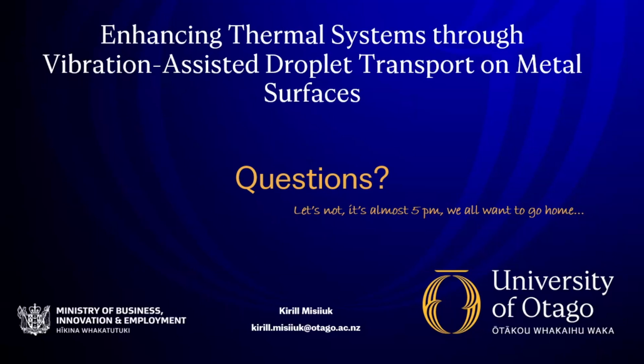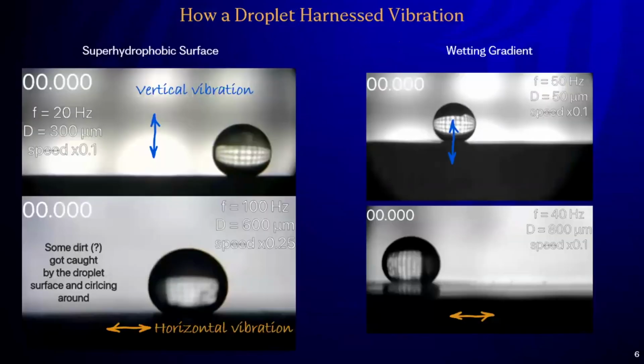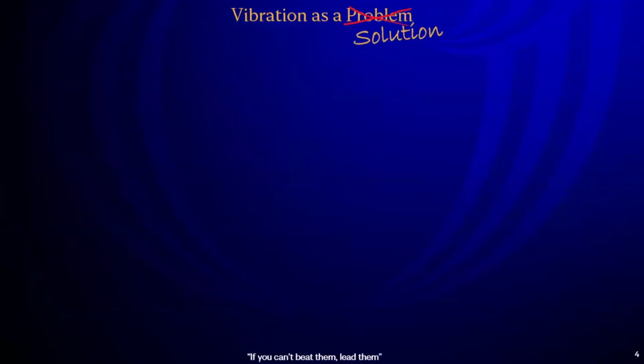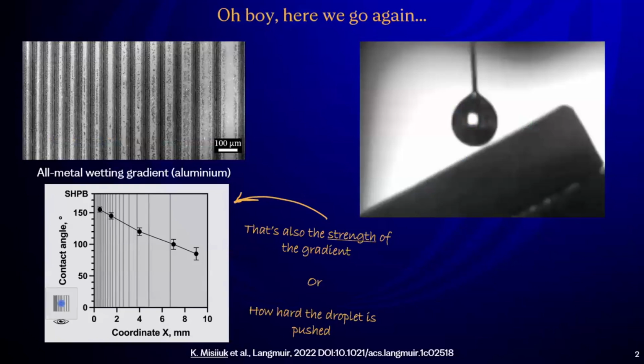So yeah, I skipped most of the manufacturing. For the manufacturing, we do laser ablation. So we literally create a microstructure on the surface. And with metals, it works perfectly because we don't care about their transparency. With glass, it becomes a bit more tricky because it indeed changes the transparency, and especially the denser the structure is, the less transparency we have.